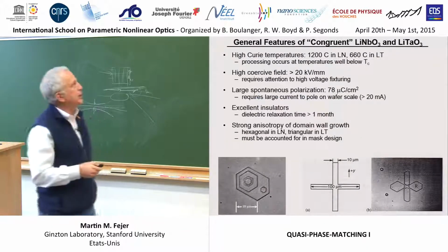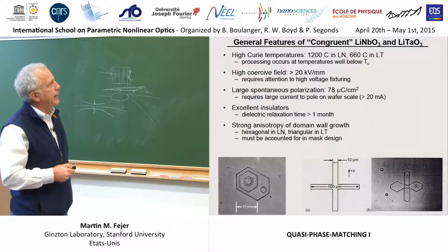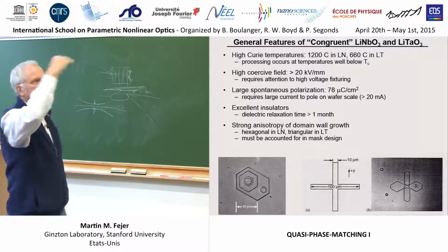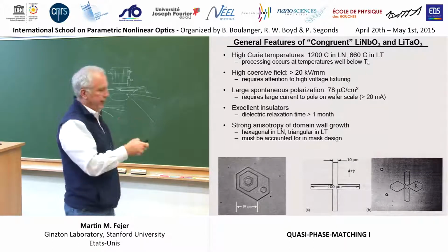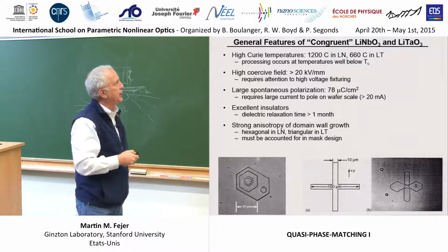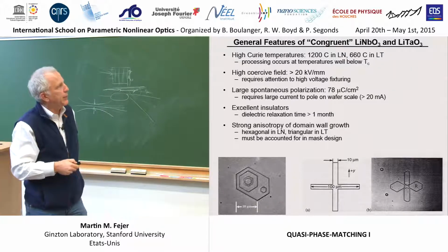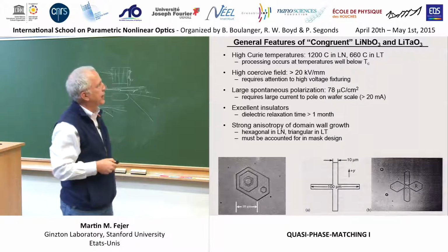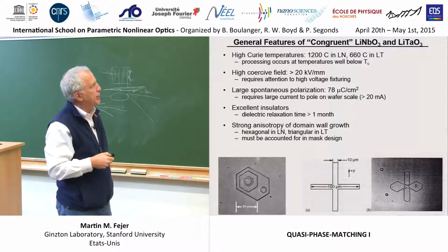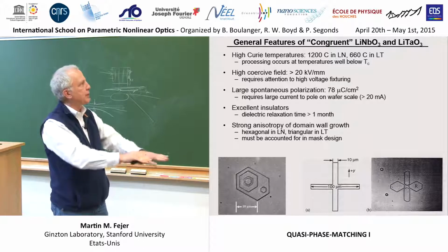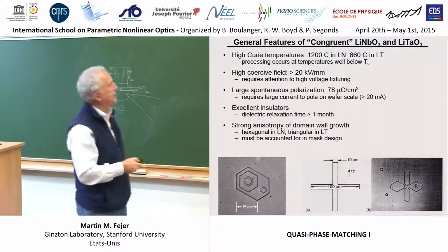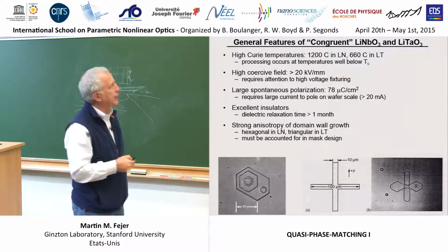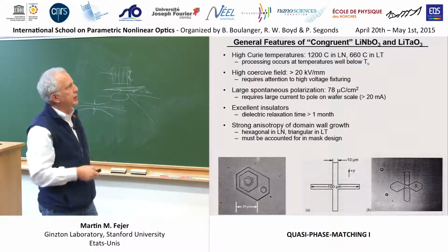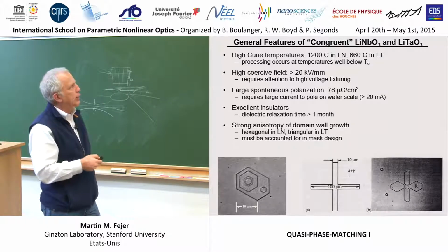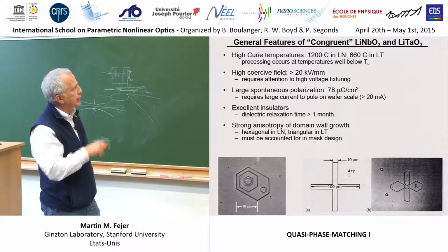So like I said, these materials have a high transition temperature between the paraelectric and the ferroelectric phase, very close to their melting temperature. In the case of lithium niobate, still very high even in lithium tantalate. So our processing is always occurring way below the phase transition temperature to the ferroelectric state. As I said, the coercive field, when you're well below the transition temperature, is quite large, of order 20 kilovolts per millimeter for both these materials.